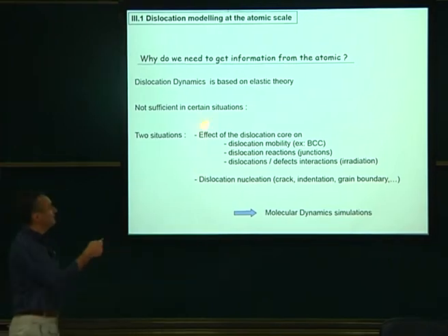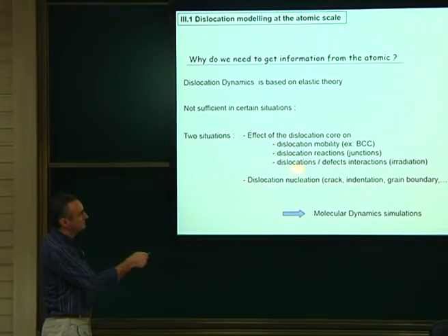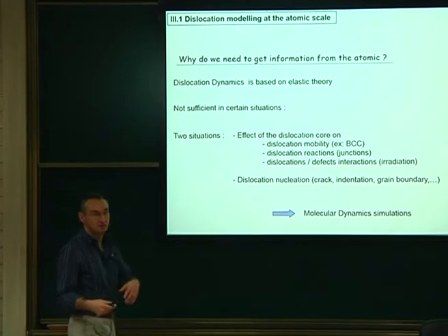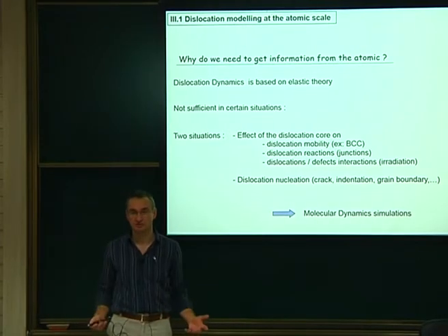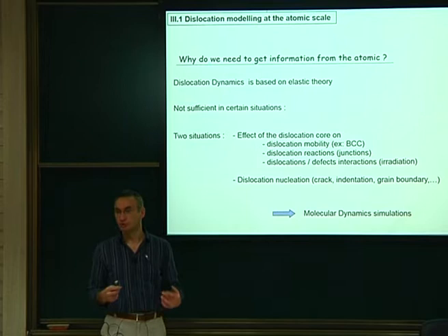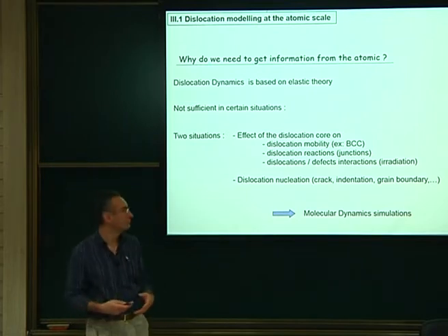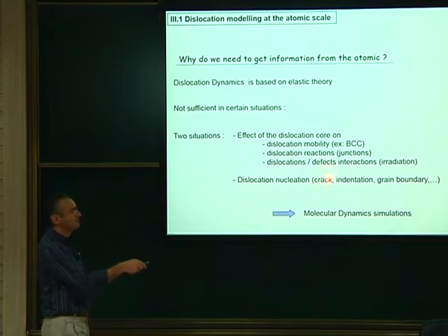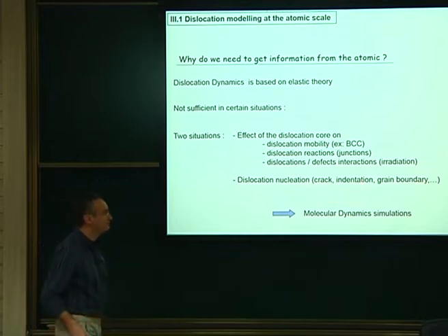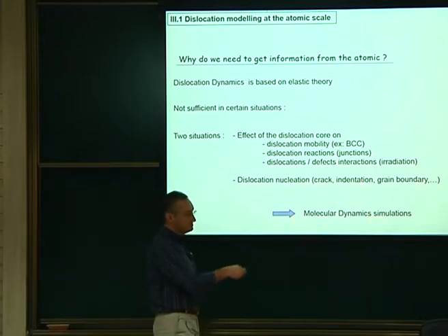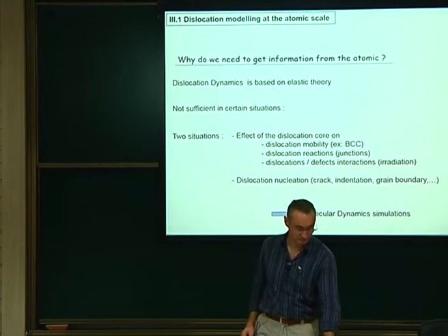And finally, another aspect is the effect of dislocation nucleation, because in DD, we know how to propagate dislocations and multiply them with Frank-Read sources, but we don't know how to introduce new dislocations. This has to be specified in the model. It could be the case for cracks, for indentation, for grain boundaries. So all those are the places where we typically need molecular dynamics to analyze these problems. So this is the need for MD simulations.